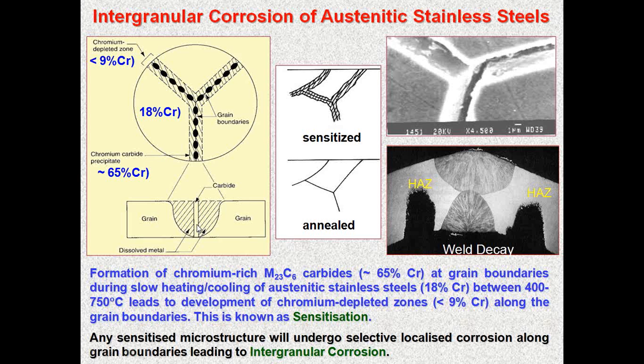This phenomenon of forming a chromium depleted zone due to the chromium carbide formation, whenever stainless steels are heated between the temperature range of 400 to 750, is called sensitization. Always any sensitized microstructure will undergo selective localized corrosion like pitting or intergranular corrosion, and this is unavoidable in service whenever you are using austenitic stainless steels.